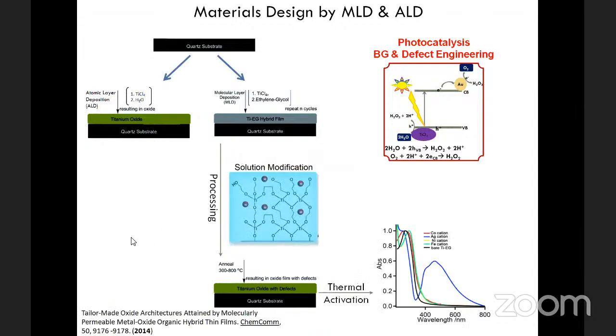And here is an example where we synthesize the thin titanium ethylene glycol hybrid film by molecular layer deposition. We incorporate metal ions, cations, and then anneal the material, and we get very controlled doping. As you can see here, this is the optical absorbance spectroscopy of such films, which are just a few nanometer thick. And you can see that we can incorporate almost any dopant very controllably and very easily into this material.